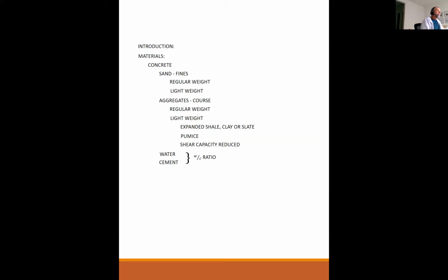So the water cement ratio for a mixed design is key to achieving certain design strengths. The more water you put in, the less strength you're going to get out of that mix. So the water cement ratio directly affects the strength. For example, you could have a mixed design with a water cement ratio of 0.5, 0.55, and my understanding is something in that range is really best used for something like sidewalks or slab on grade, where the strength really doesn't matter too much, because that's really about a 2500 psi mix. Not very strong, but really, really easy to pour.